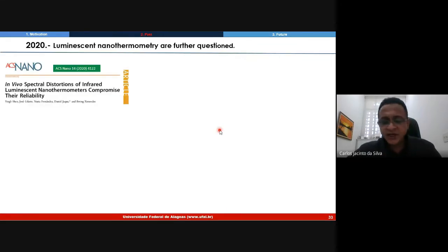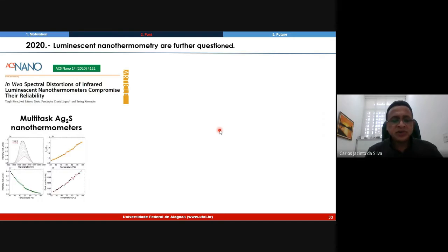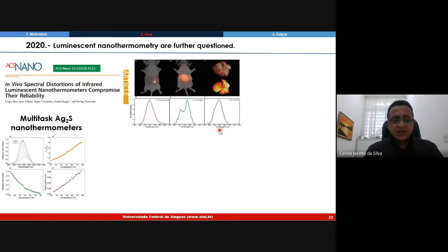Even using the silver sulfide nanocrystal, the luminescence nanothermometer has been questioned. This material is a multitasking nanothermometer because it presents thermosensitivity in intensity, peak position, bandwidth, lifetime, etc. The similarity between the image spectrum and the difference is attributed to the wavelength-dependent attenuation of the tissue between the liver and the detection system, including vessel, skin, etc.